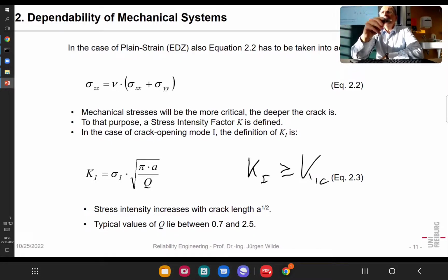Now if you have that load-strength concept, you can say, depending on what the material is, depending on whether I have a crack or not, I take another physical property for load and strength. There are also some cases where we do not use stress, but we use strain, for instance. We also can have energy criteria, but again, to the left, that's the load, and to the right, that's the strength, and the strength is always the material property. That criterion looks simple, but it is extremely helpful.